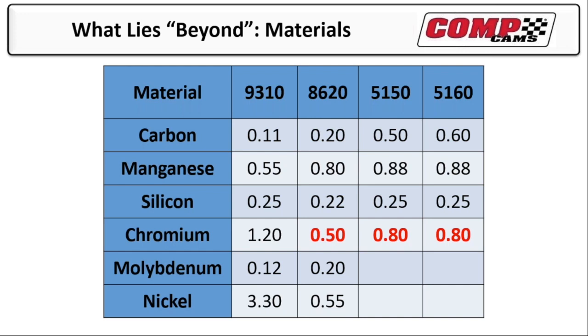So somebody tells you, well, what's 52100? Well, that's easy. It's a 52 series steel with 1% carbon. What's 8620? It's an 86 series steel with 0.2% carbon. So what makes the first two numbers? Well, it's what lies beyond that. So 8620, very common steel, is 0.8% manganese, 0.22% silicon, 0.5% chromium, 0.2% molybdenum, and 0.55% nickel.